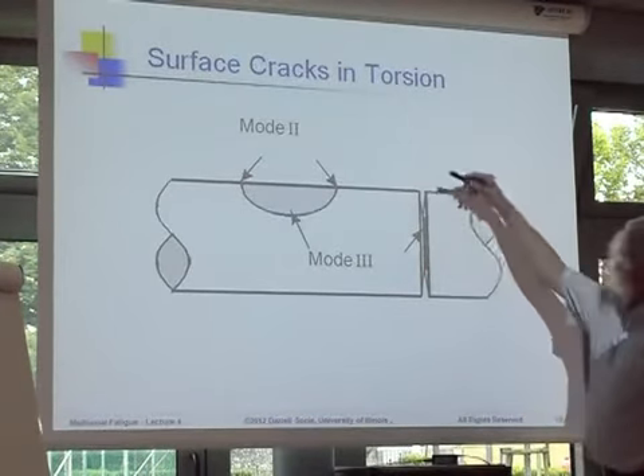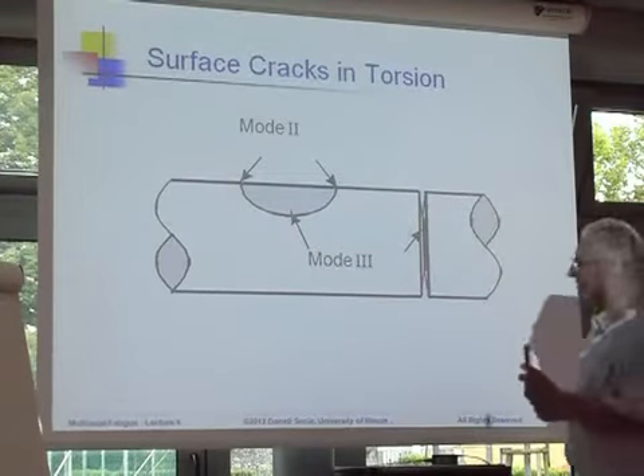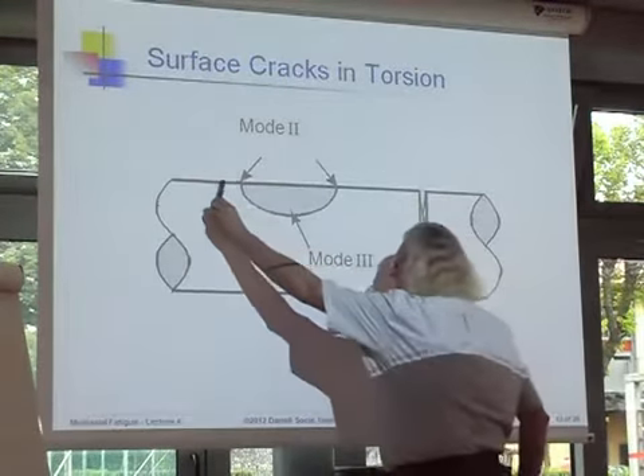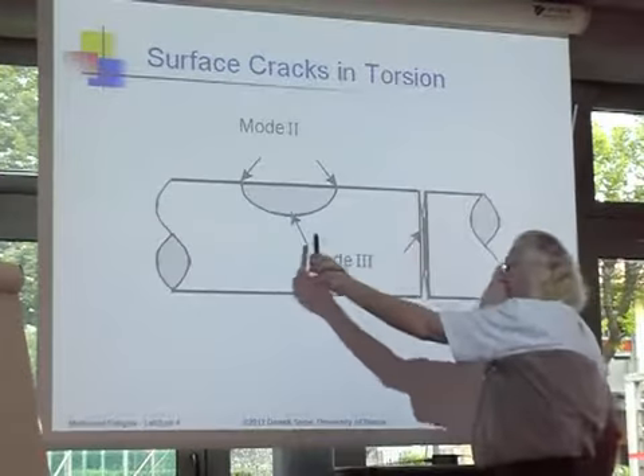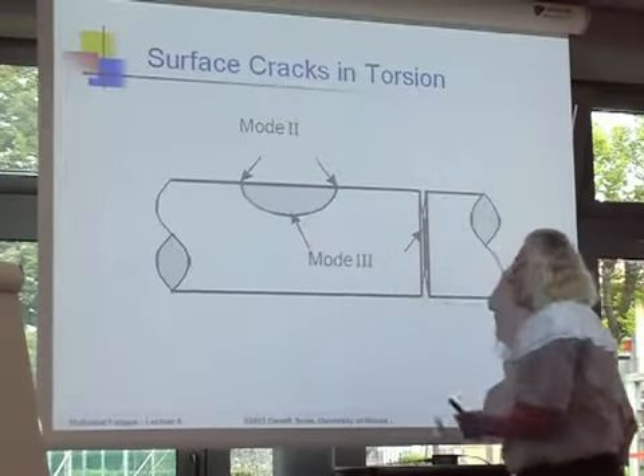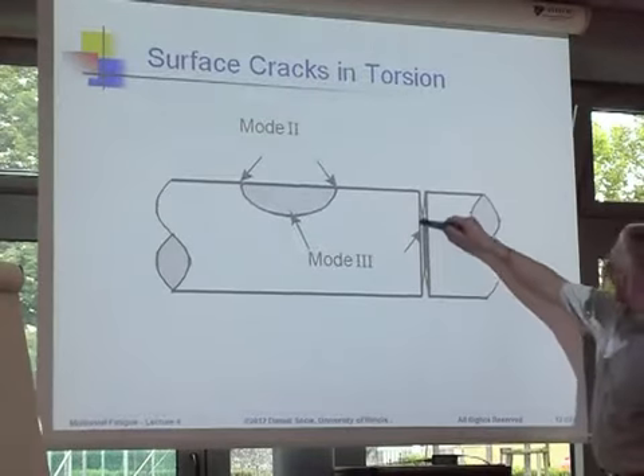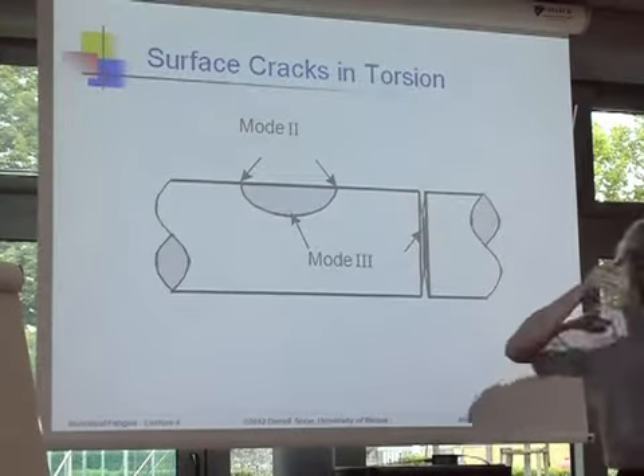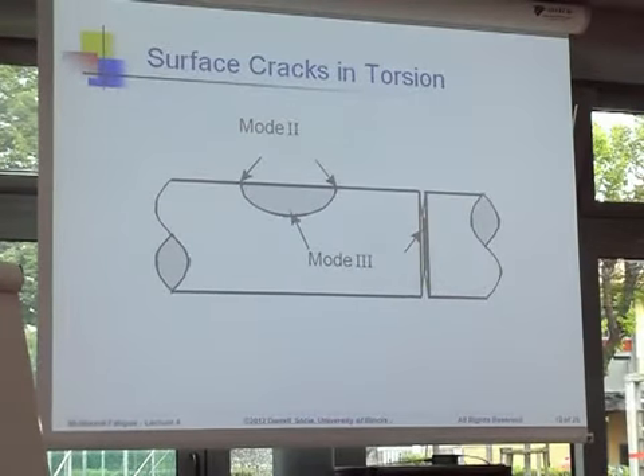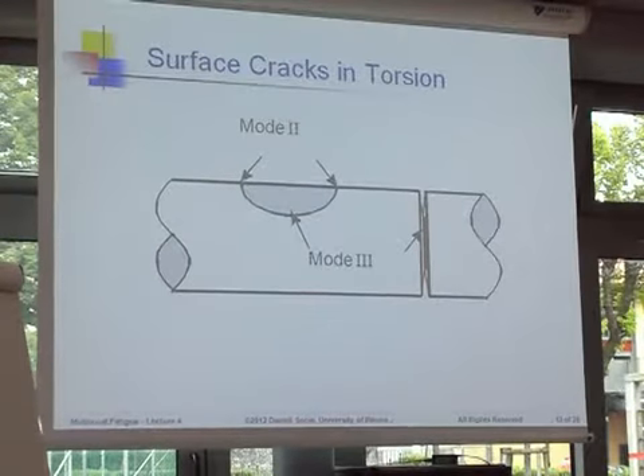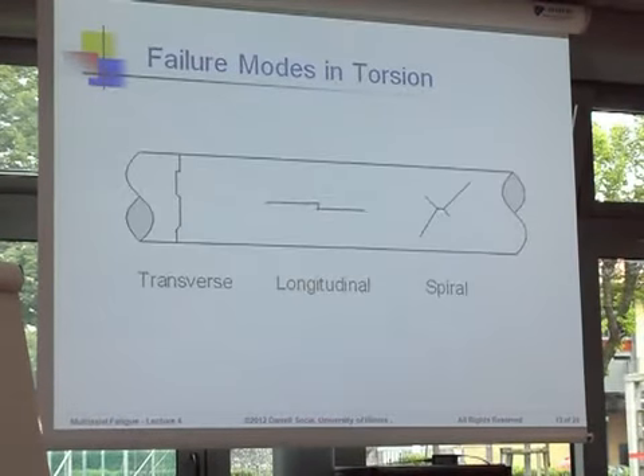Or you could have a circumferential crack like this. This crack is growing along the surface in mode 2, and it's growing in the depth in mode 3. And this crack, a circumferential crack, is always in mode 3. So in shear loading, let's look at the growth rates.